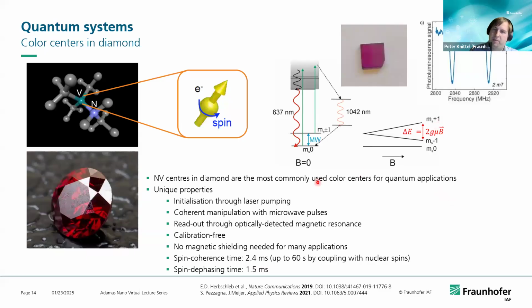And this is what you actually use for quantum sensing and quantum computing approaches. If you make use of it in quantum sensing, you can, for example, measure magnetic fields. This MS ±1 state is degenerate, and as soon as you apply a magnetic field, it undergoes Zeeman splitting. This leads to a split into MS -1 and MS +1, and also due to this non-radiative path, if you drive the NV center with a microwave, you get dips in your fluorescence, and depending on the distance between these dips, you can see how high the magnetic field is that the NV center feels. So this gives you a magnetic field measurement without any additional calibration.